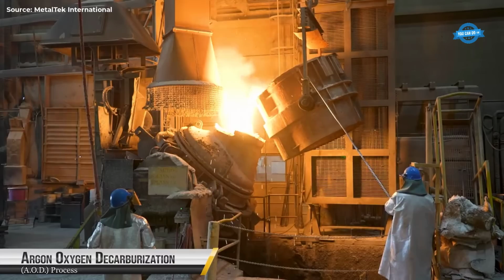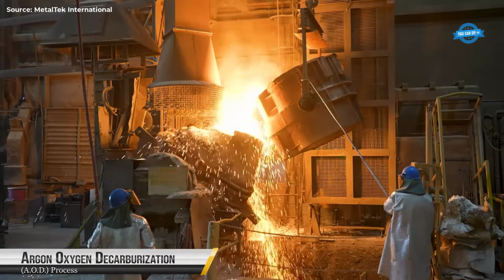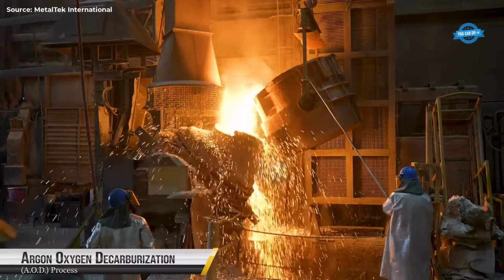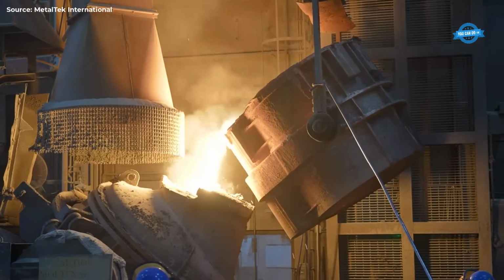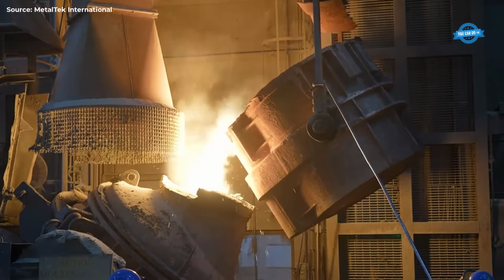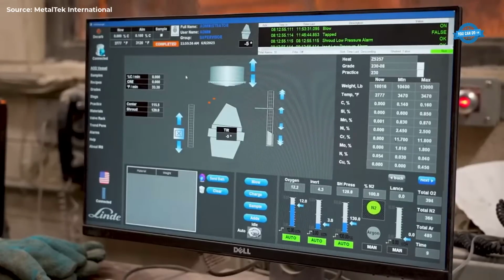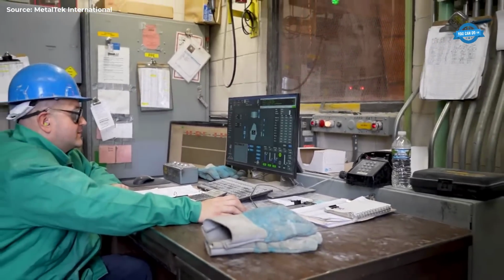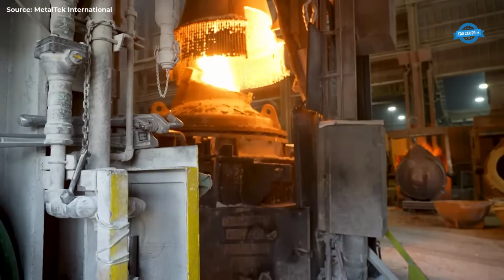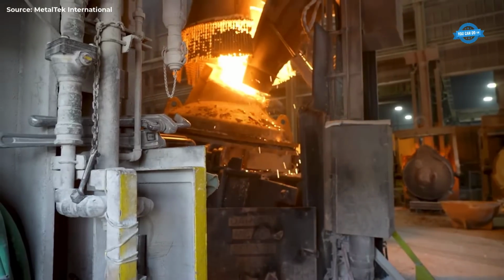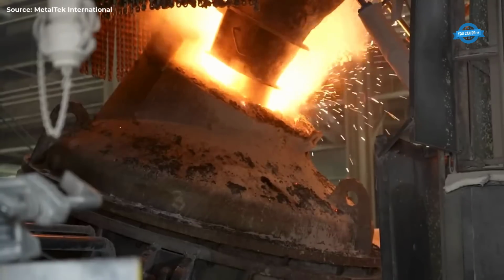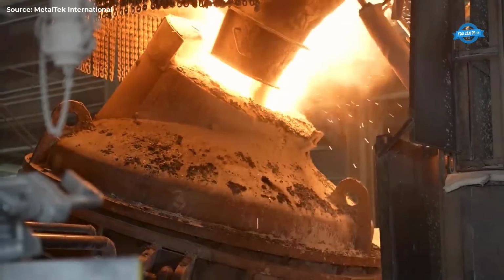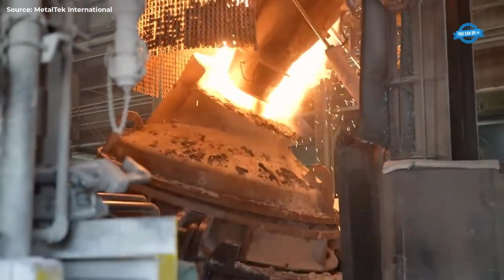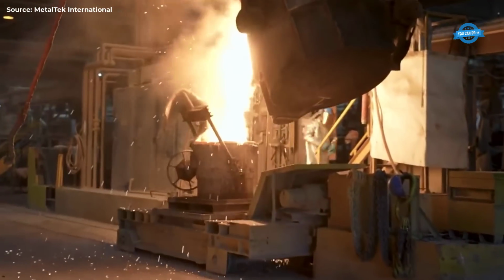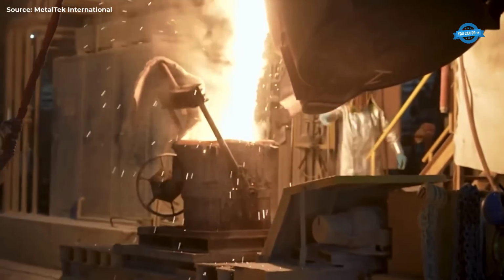Argon-oxygen decarburization, AOD, is a refining technique used to improve the physical properties of stainless steel and other ferrous alloys. The process begins with charging the AOD vessel, which is preheated and typically contains molten metal from an arc furnace, along with specific alloying elements and additives. Once the vessel is charged, a mixture of oxygen and argon gases is injected into the molten metal. The oxygen reacts with carbon in the steel, forming carbon monoxide, which is removed from the vessel, reducing the steel's carbon content.